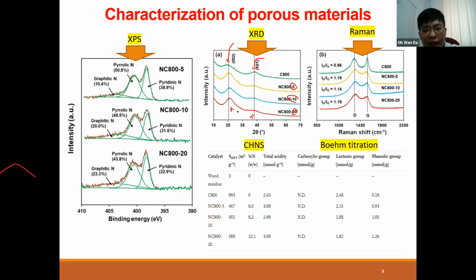Another thing that you can look at to confirm that you have amorphous phase is the background. So the background is like this, right? It's not really straight. It's moving down, slanted. So this means that you have amorphous compound, which means that the background is quite high in terms of the noise. If it's crystalline, then you will get very sharp peaks. Of course, sometimes you have crystalline materials that do not give you such sharp peaks, but the background is not going down. It is straight, but the peaks are not so sharp.